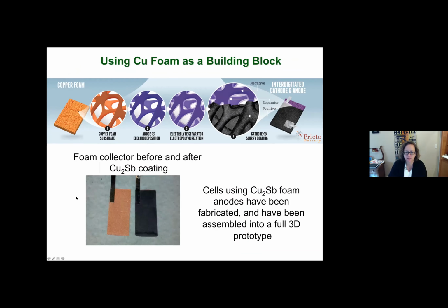So the electroplating is quite fast. What I'm showing you in the photograph on the bottom left is the copper foam with a tab that's ultrasonically welded. And that contact tab is actually quite important. That also has to have pretty low impedance to have good performance. And then the image on the right is one of those foams after a 2-minute deposition of the copper antimonide, and it is conformally coated. There are no binders, there's no post-processing. It's just a very thin layer of a dense electrochemically active anode material.